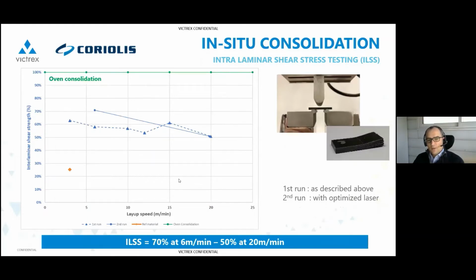And finally, again, we might be challenged on that. It's maybe far from being perfect. We chose ILSS, interlaminar shear strength, to evaluate the mechanical strength of the coupon. Just to make sure we're on the same page, we normalized the results, and the baseline was the coupon consolidated by oven consolidation. So we know the best we can achieve is via a post-consolidation process. Let's say this one is 100%.